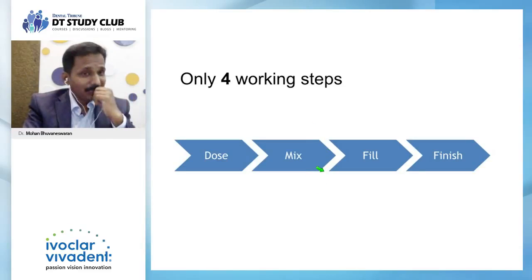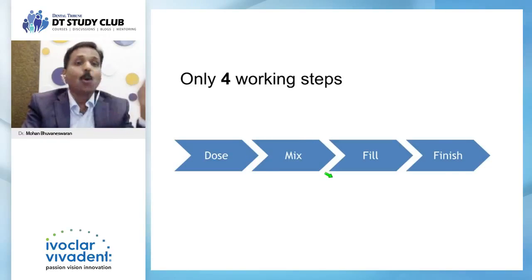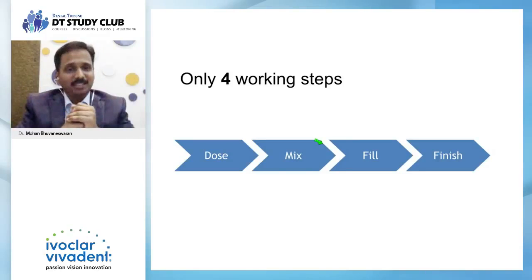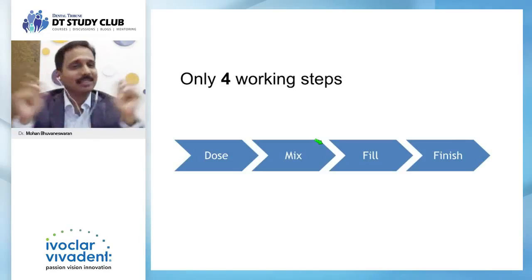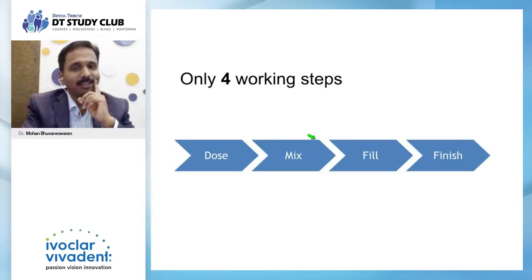How many of you actually do it? You're supposed to use a polyacrylic acid to remove the smear layer. Only then the so-called big advantage of glass ionomer, the chemical adhesion, happens. Otherwise, chemical adhesion is a myth. How many of us do it?